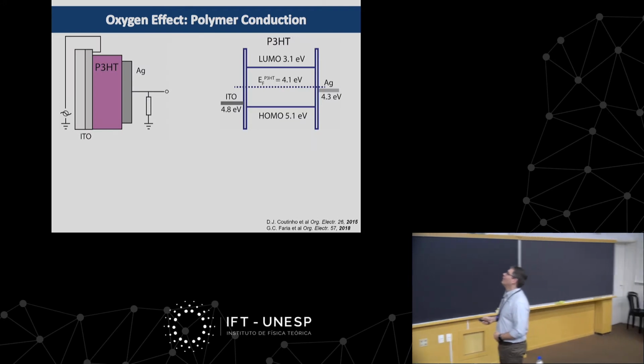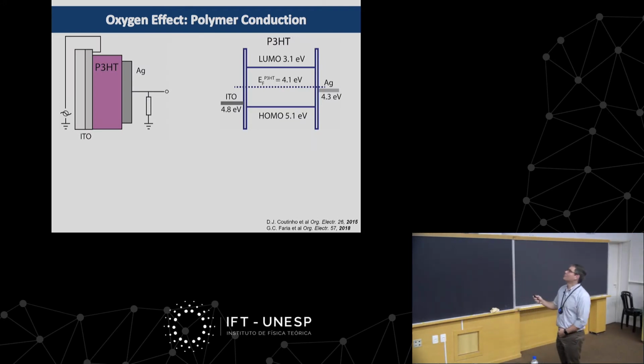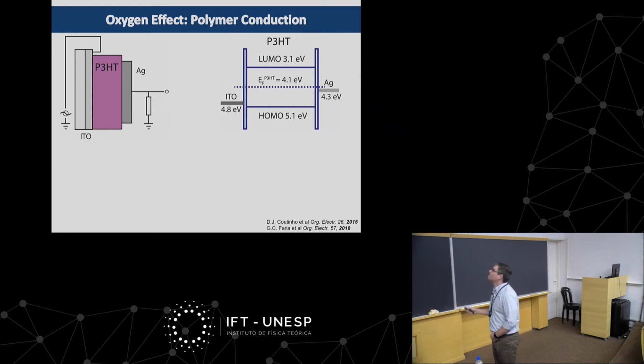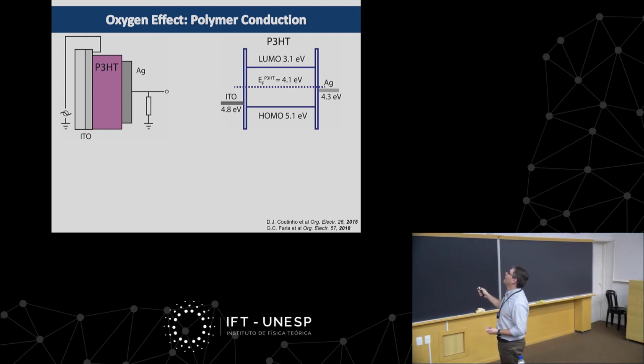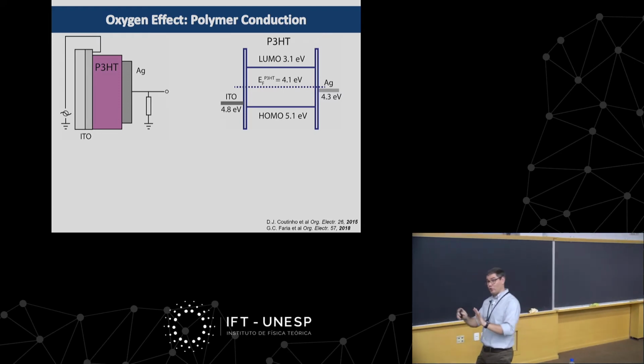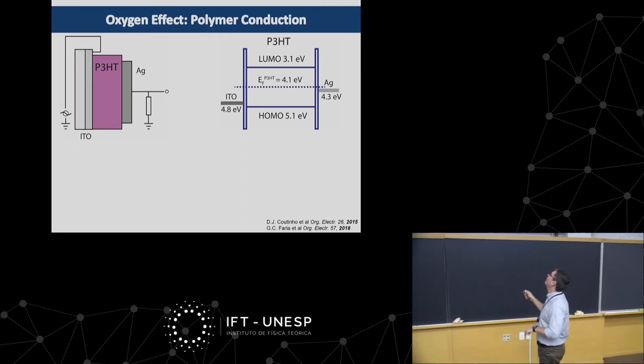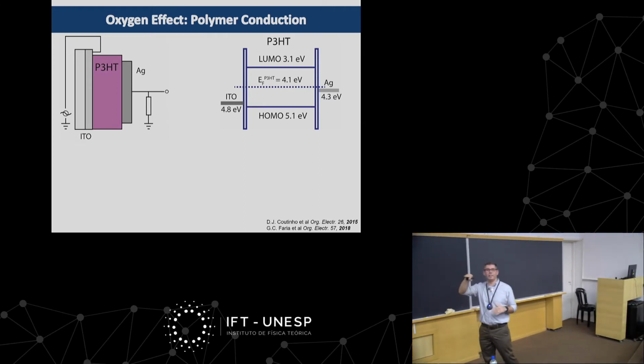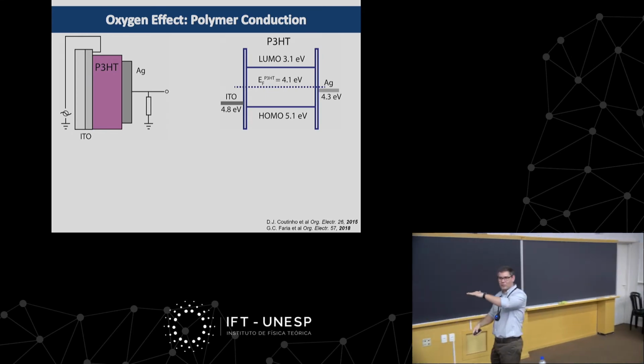But okay, so we got back to the drawing board, and here's the band diagram. And actually, it's quite interesting. So you see that the ITO has a work function of 4.8 electron volts. And for a P3HT that has this conduction and valence band number, if the material is undoped, there is no charge in that material, we have the Fermi level basically sitting in the middle of the band gap because this is completely filled, this is completely empty, and therefore,